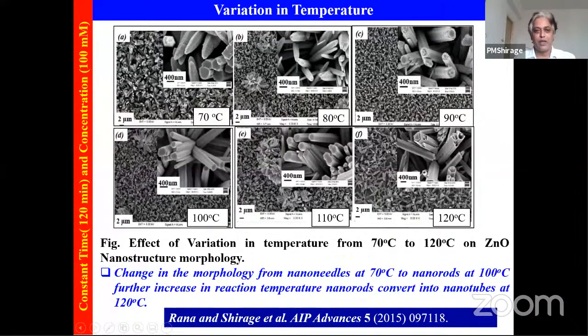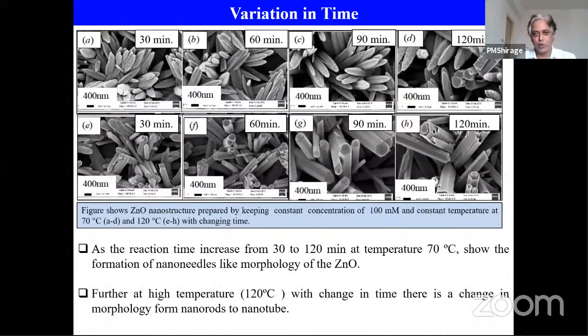It means that temperature plays a very crucial role, and controlling temperature is very important when we prepare the materials. So the morphology changes from nanoneedle at 70 degree to rod-like structure at 100 degree, then at 120 degree a tube-like structure is formed. Now, two parameters we already talked about. Now the third parameter, that is time.